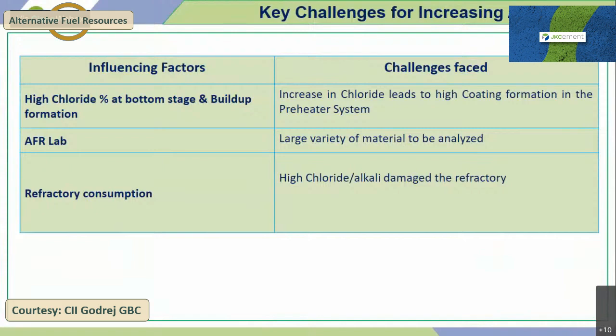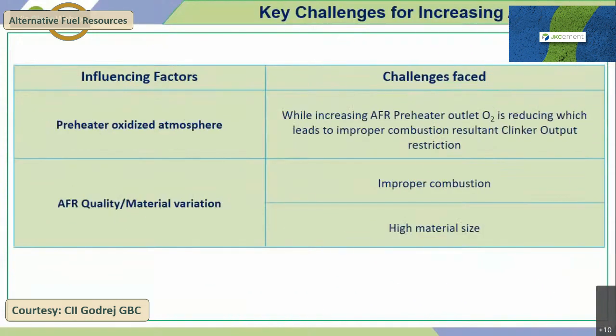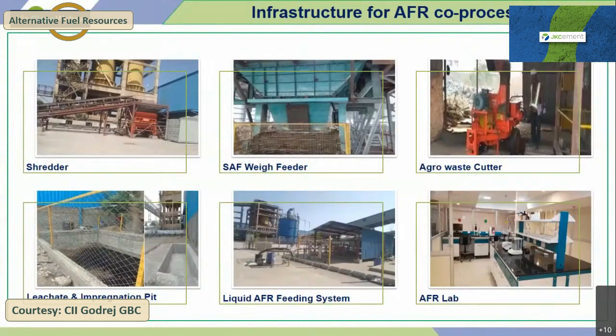High chloride in the bottom stage leads to build-up formation. And in the AFR lab, a large variety of AFR material has to be analyzed. Regarding refractory consumption, in the bottom cyclone area in the calciner and the calcining zone of the kiln, we face some problems when using higher AFR. Life is slightly reduced. And the preheater oxidizing atmosphere is not normal because frequent CO comes from AFR feeding in the calciner. So the outlet O2 is not maintained properly, which leads to a slight reduction in clinker production.